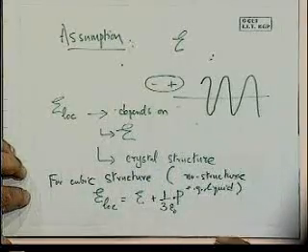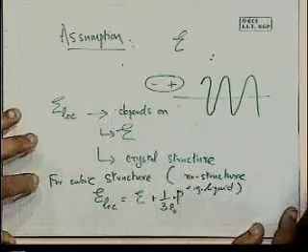This local field is also known as the Lorentz field, and in the case of the electronic polarization and ionic polarization, it is applicable, though when we start talking of orientational polarization or dipolar polarization, this idea will not be applicable, to relate it in this way. But at least for some of the polarization mechanisms, namely one which we have looked at, electronic, this idea will apply for a cubic structure, and or if there is no structure, namely in the kind of a liquid situation.